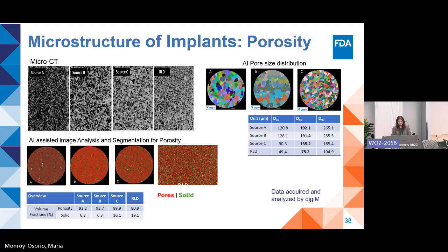So the result shows that implants A and B have broader porosity and less solid content compared to implant C, which has a denser solid content network and smaller pores compared to A and B. However, the RLD shows a very dense solid content network with the smallest pores and the greatest amount of solid content in the implant.